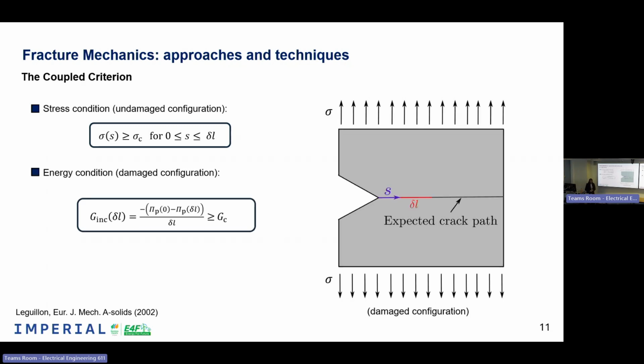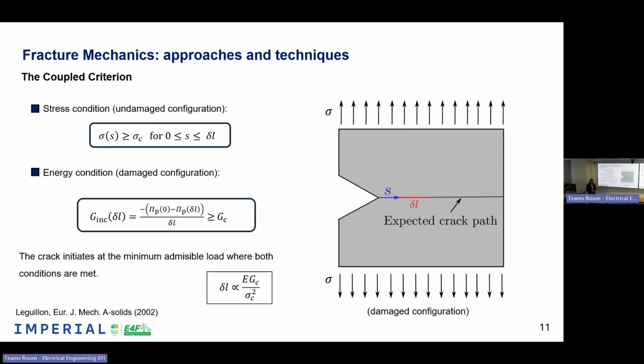Then we add the energy condition that is based on the assumption of a certain crack that has a size delta L. It is called the newly created crack length. And for this delta L, we measure the difference in potential energy, and we divide it by this newly created crack length. And we compare this value with respect to the material property that was created by Griffith, the guy I mentioned before. It was the critical energy release rate. So when both conditions are fulfilled, at the minimum admissible load at which it is fulfilled, we will have crack nucleation. And as a consequence of the application of this criterion, we will have a new crack nucleation length that is proportional to the material properties, as you can see here. This crack nucleation length represents a first jump that the crack does when it is nucleated.